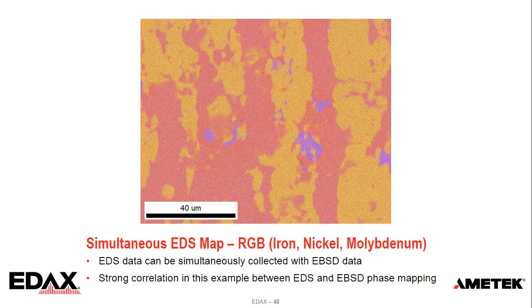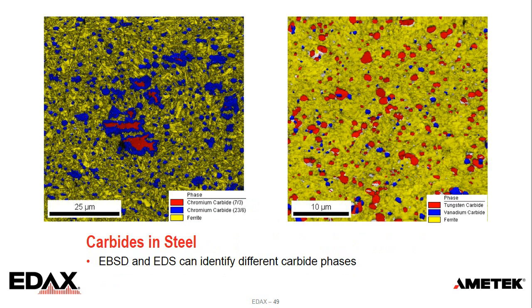This is just an example of looking at different carbides in steel. On the left here, these are different MC carbides, where M is chromium in this case. So we're looking at a 7-3 carbide and a 23 carbide, the blue one, and you can see how they're distributed. They have a very interesting structure. Some of the carbides have an interior-exterior carbide distribution. On the right, this is looking at tungsten carbide and vanadium carbide in a ferritic matrix. We can see where they're present. So, carbides, we can resolve those out nicely.